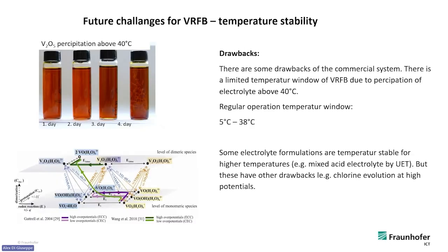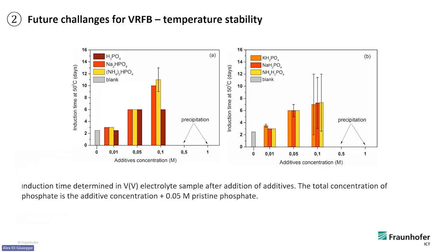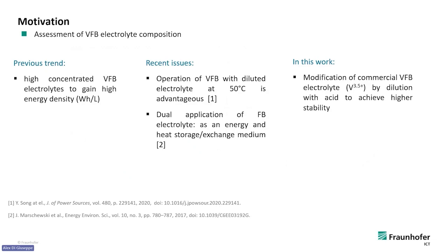But it has some flaws. When you increase the temperature, you will notice that the chemistry will change, and it's a very slow process, but it happens that you will have precipitation. And this 40-degree or 38-degree upper limit is only for the charged electrolyte, but it is inevitable. So usually you cannot use vanadium electrolyte as a heat storage. You can try to use additives, some phosphates, and you will get a longer induction period. So instead of it taking place in 2 days, it can take up to 6 days, but you cannot avoid it. So in our study, what we did for the BFlow project, we looked at a different strategy.